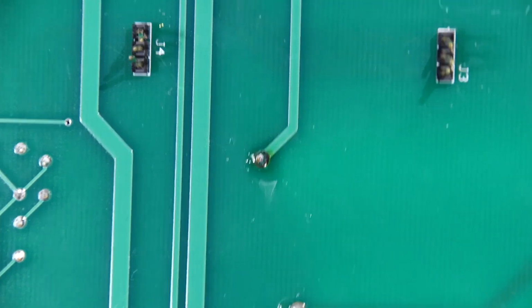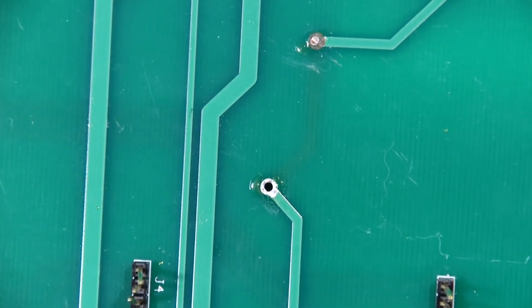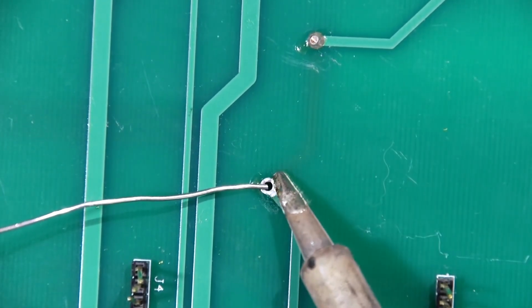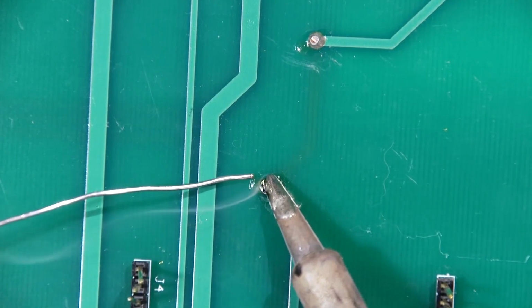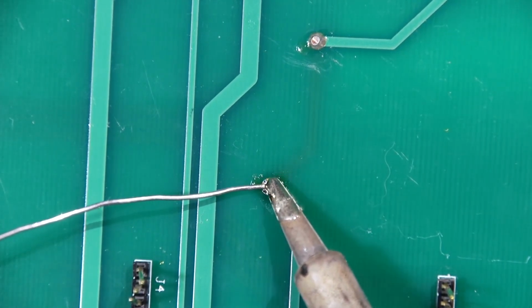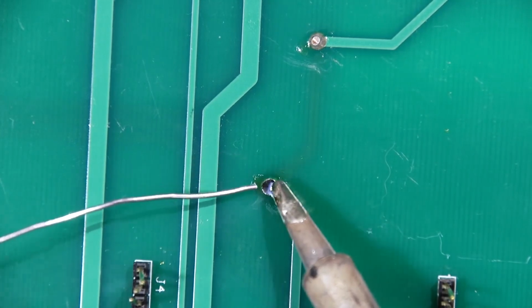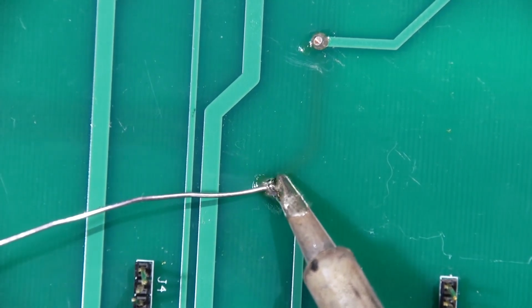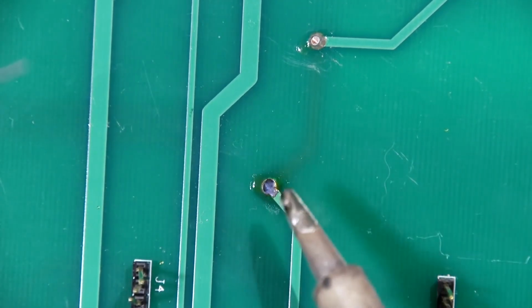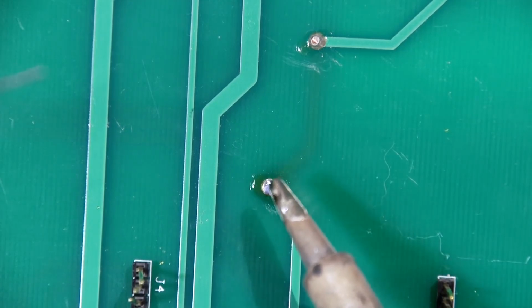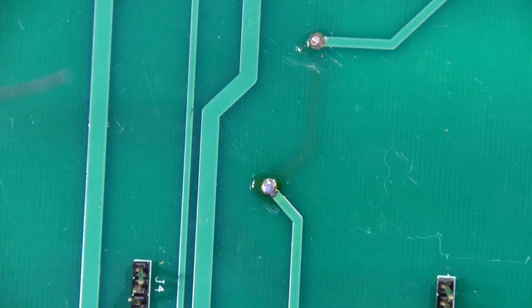If I was to solder this other one here, you can see that there's nothing in there. It'll just fill the hole at this point. Let's give you an example here. You can see it'll just start to fill the hole. See that little hole? It's going down through the hole. Now, if you've pulled a plated through hole out, if you've pulled that little barrel out of the center, it won't do that. The solder will just sit on one side of the board, and it won't connect to the other side of the board.